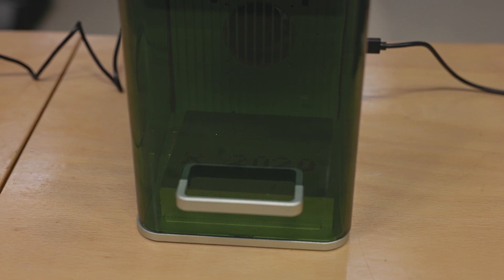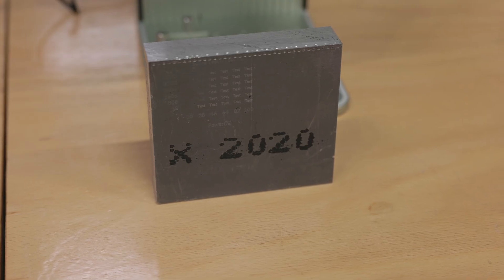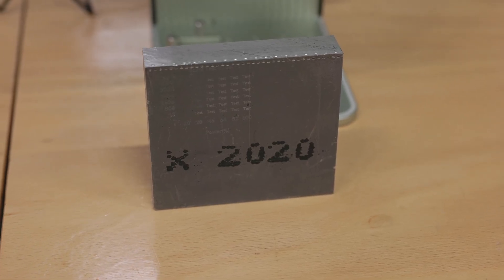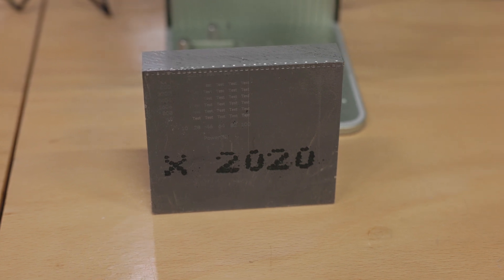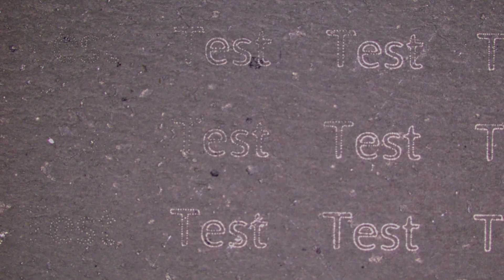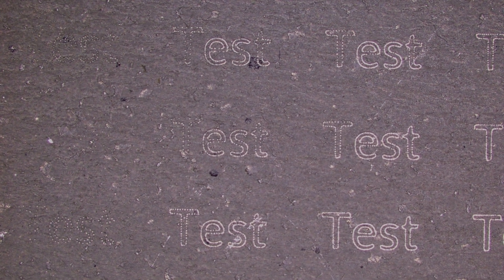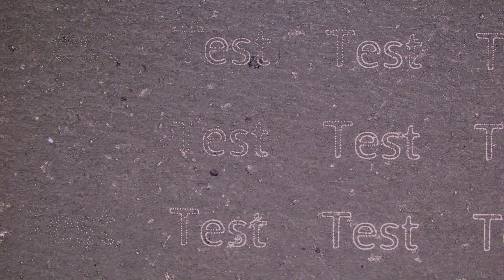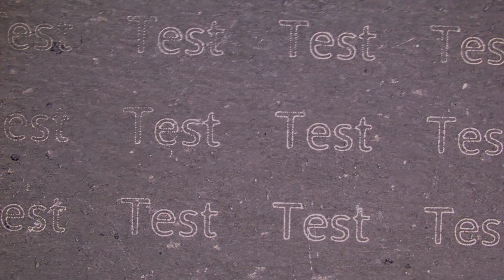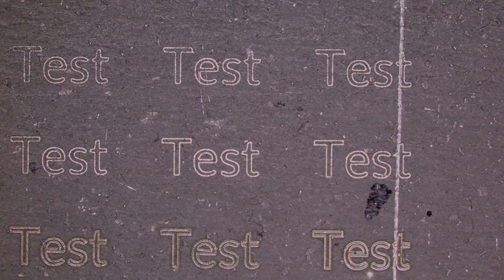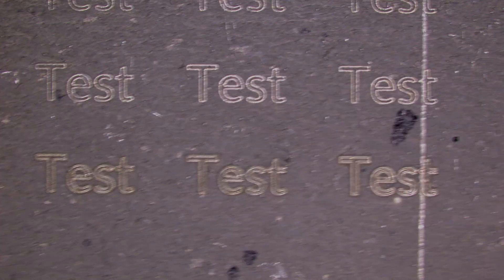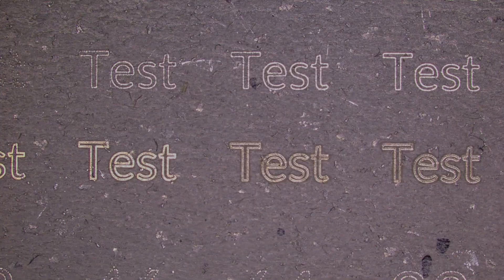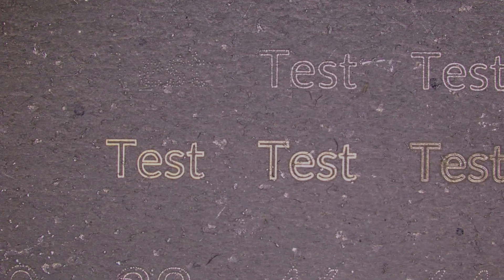After the engraving was done, I took the part out, and there was immediate success. You scored a little bit of font onto it. Taking a closer look at the font under our microscope, you can see that at high speeds and low power, there is not enough dwell time to really form the font. But at higher powers and lower speeds, you actually get really nice font.